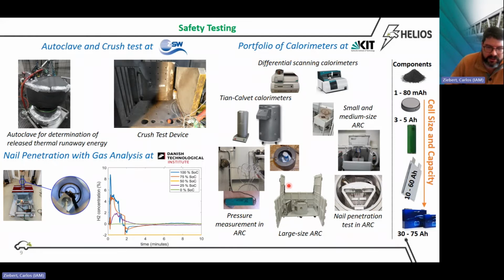So this is also important to consider, that you always have to compare cells which are freestanding with cells that are in a setup that is also later used in the application in the battery pack. Then we have the ZSW, where we are measuring the released thermal runaway energy in an autoclave and also doing gas analysis. Then we have the Crush Test Device. At the Danish Technological Institute, they have set up a nail penetration system together with gas analysis.